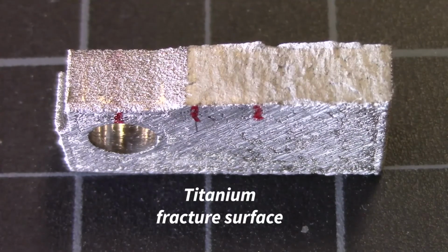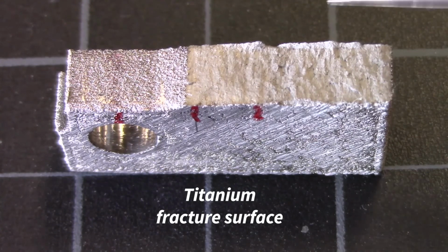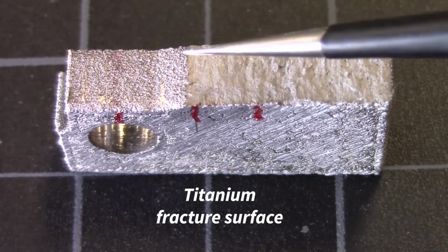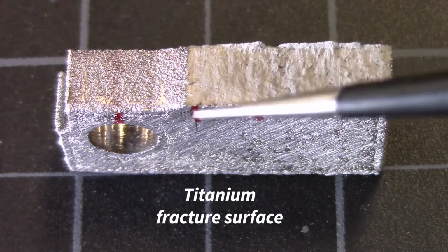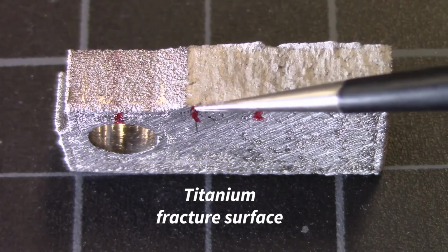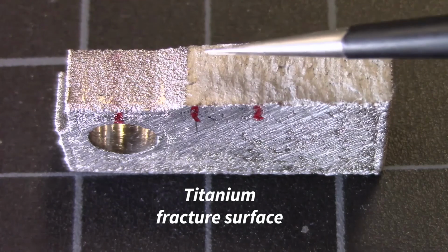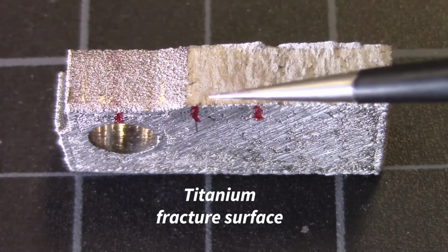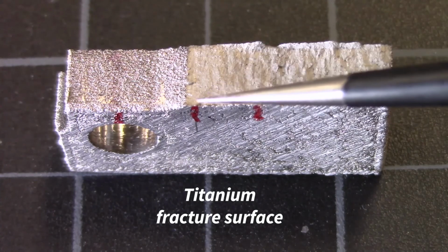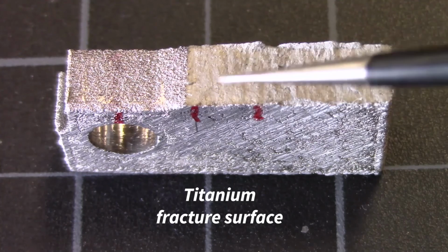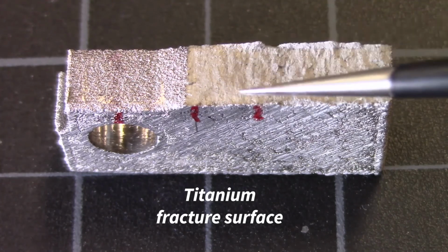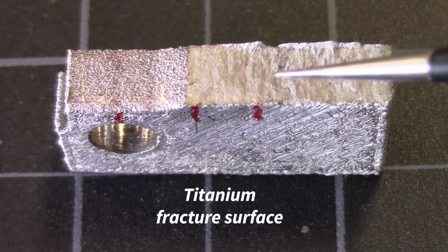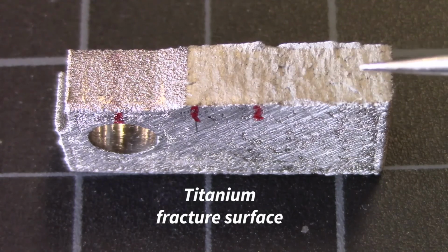And finally, here's the titanium specimen after fracture. It's a little less obvious where the regions transition, but here's our starter crack edge. This is where our pre-crack ended. There's a slight change in color. It's hard to pick up on the film here. We have a crack propagation region all through here, and then after that, this rougher surface is after fracture.